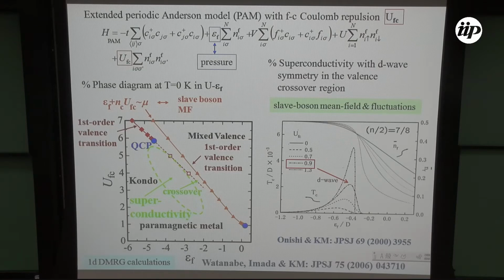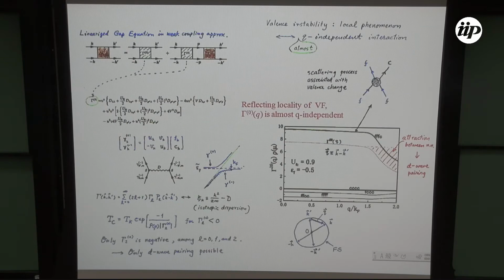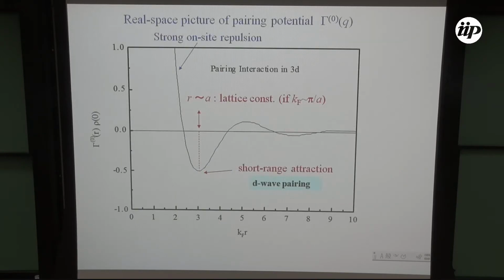Let me see this parameter. And we discussed taking the fluctuation around the slave boson mean field, we can obtain the superconducting interaction, which is almost constant up to 1.5 kF, then decreases. If we take the Fourier transform to real space, this is a strong on-site repulsion and inter-site attraction, which is the origin of d-wave pairing.